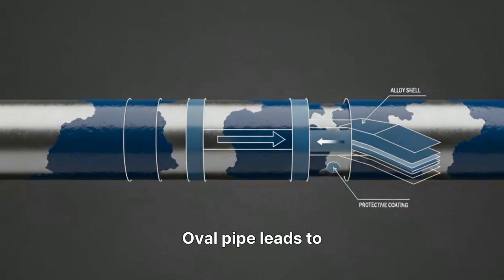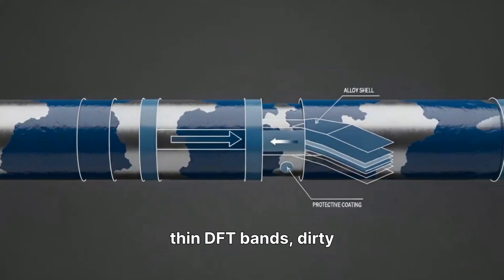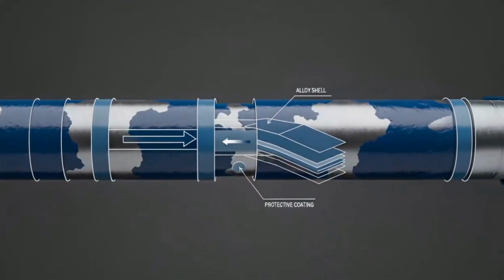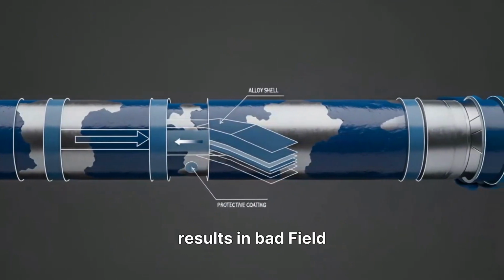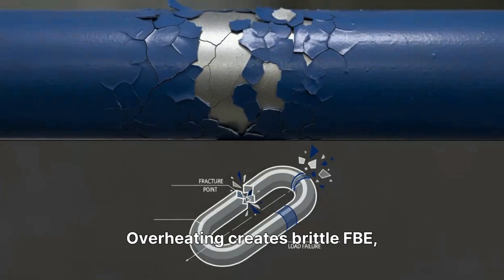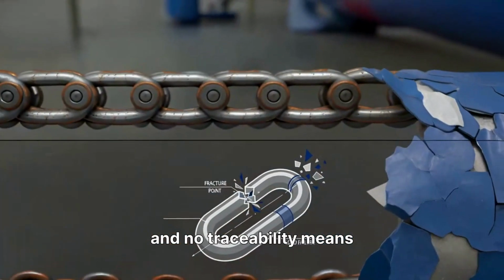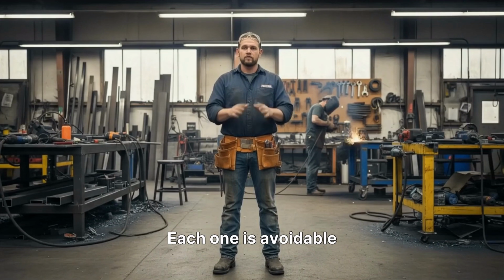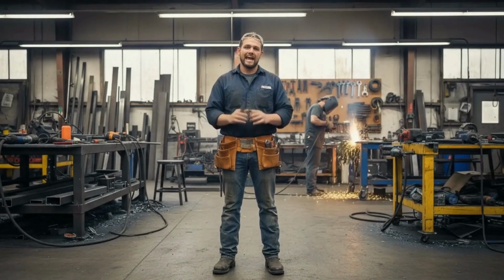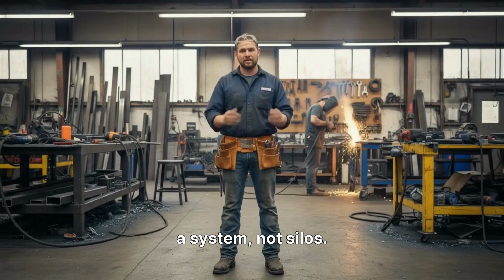Failures happen when the two standards aren't aligned. Oval pipe leads to thin DFT bands, dirty steel causes adhesion loss, and a wrong cutback results in bad field joint coating. Overheating creates brittle FBE, and no traceability means no accountability. Each one is avoidable when API 5L and NACE are treated as a system, not silos.